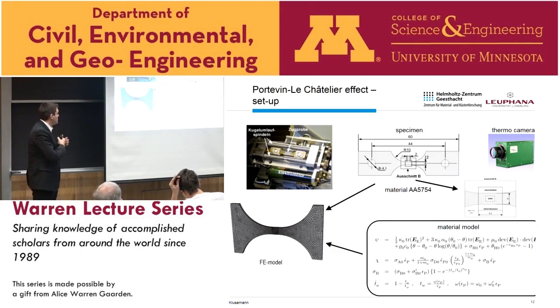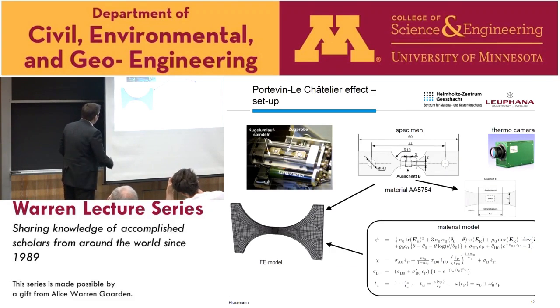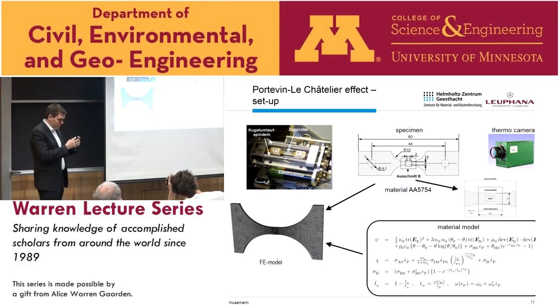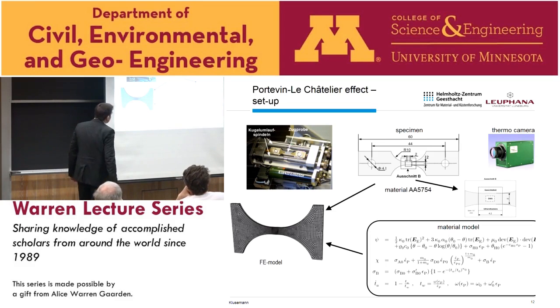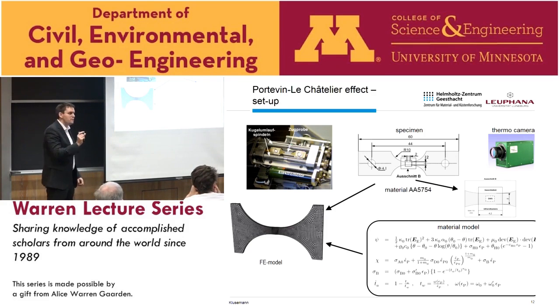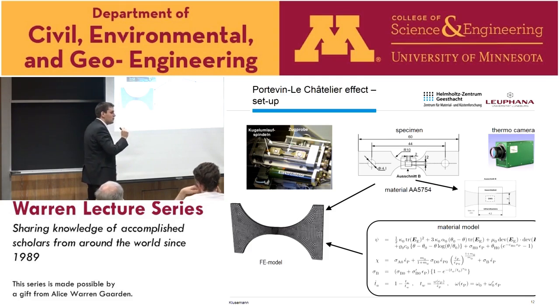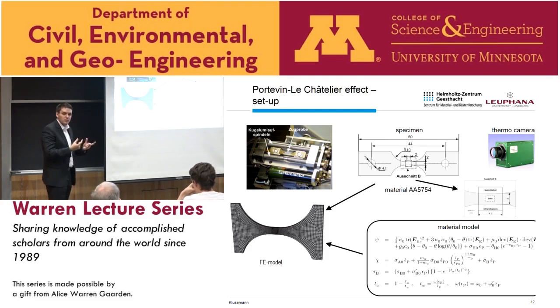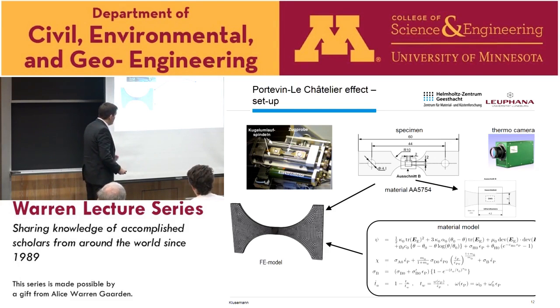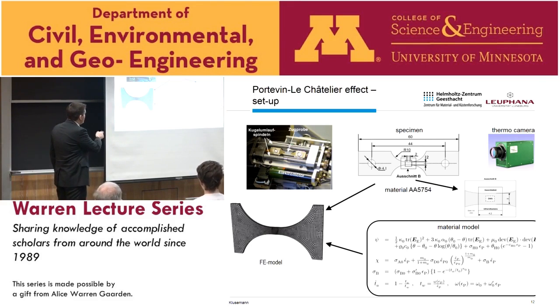Okay. So we investigated that again from an experimental point of view as well as a numerical one. Here you see our experimental setup, which is just principally mini micro tensile specimens of this size. Every dimension is given here in millimeters. And the important thing is that we have a gauge length of only 2 millimeters. Why did we choose such a small length? Well, the reason was that we wanted to avoid having more than one PLC band in our sample. We just wanted one PLC band which we can then distinguishably detect based on the thermocamera as well as on strain gauges. That's why we used such a small local region.